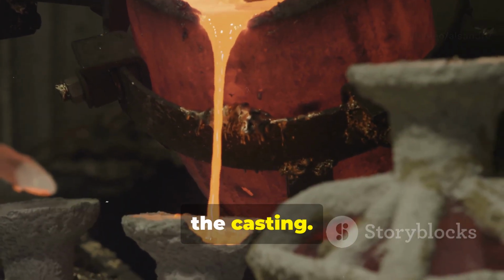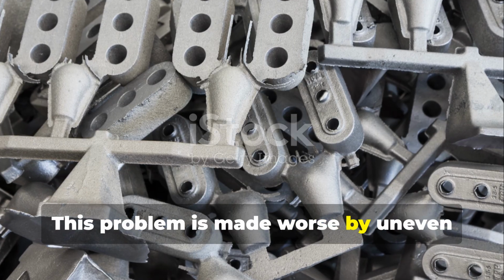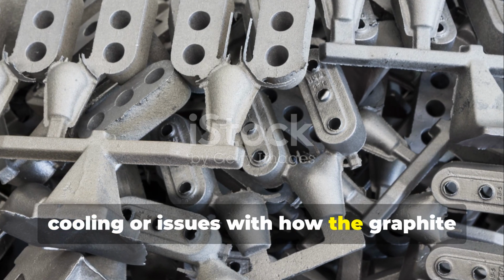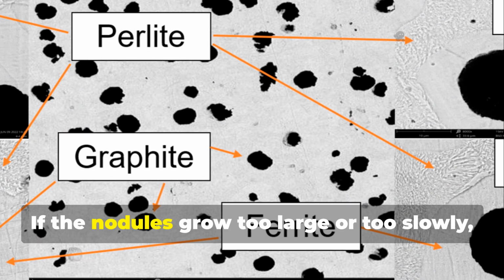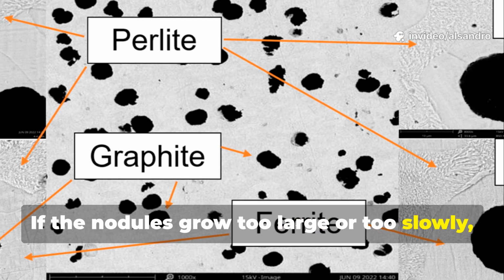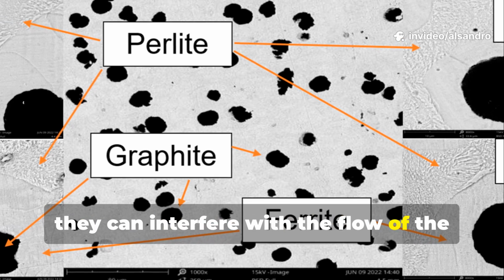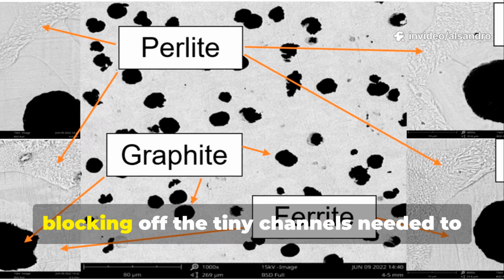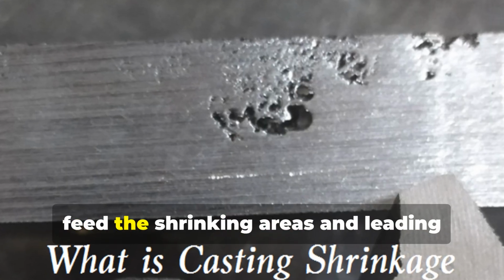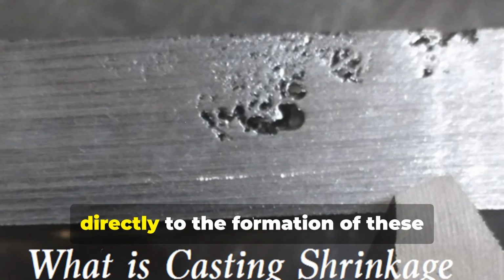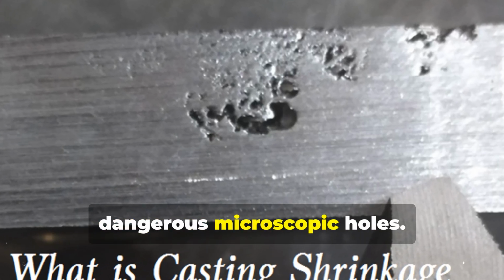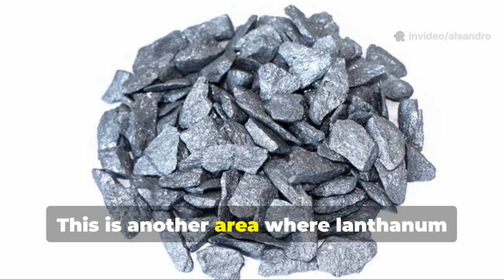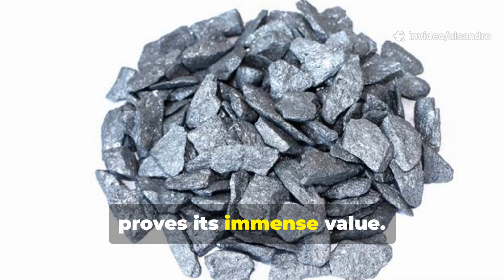This problem is made worse by uneven cooling or issues with how the graphite nodules are growing. If the nodules grow too large or too slowly, they can interfere with the flow of the remaining liquid metal, blocking off the tiny channels needed to feed the shrinking areas and leading directly to the formation of these dangerous microscopic holes. This is another area where lanthanum proves its immense value.